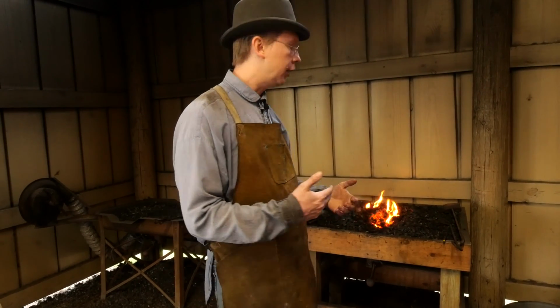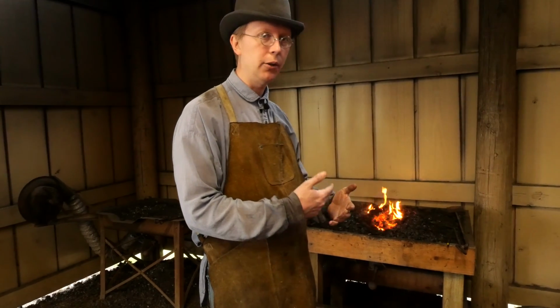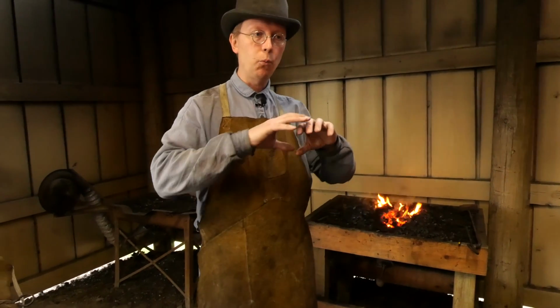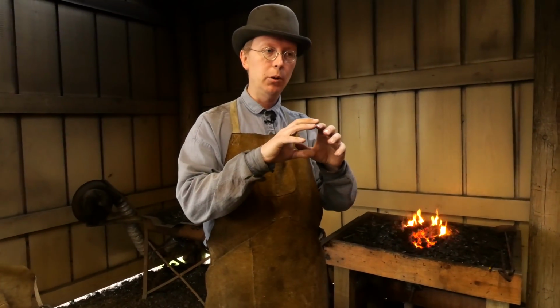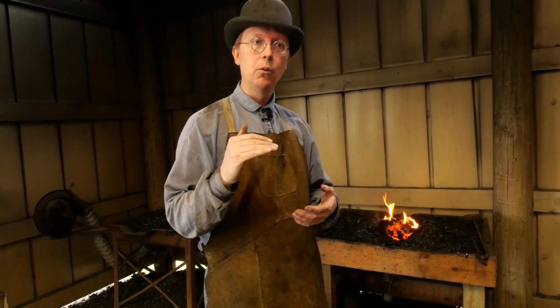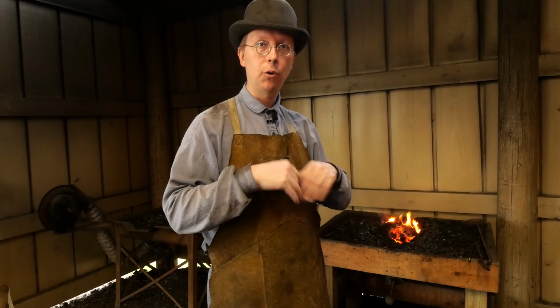Honestly though, when I'm welding up mild steel, I normally don't bother using flux. What the flux is going to do for you is, one, it'll melt onto your steel and it will provide kind of a glassine coating over the steel, which will prevent oxygen from getting to it, which will reduce the amount of scale that builds up. Scale is not weldable, so if you've got a weld with a piece of scale in the middle, you've got an inclusion and you've got a spot where it's not welded. The flux will also help lower the melting point of that scale a little bit, which can make it easier to get all that into a liquid form and pushed out so you can get a good clean weld.